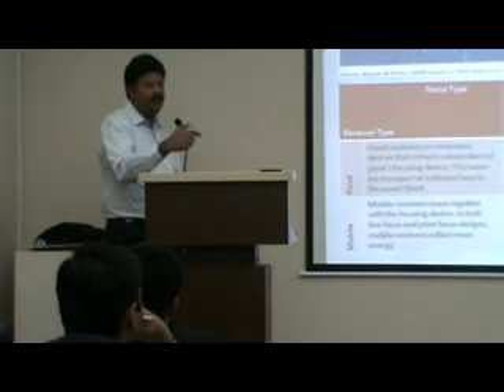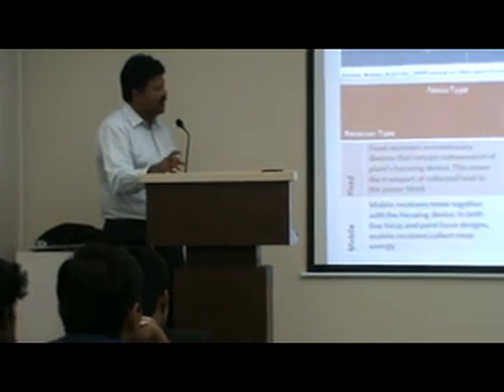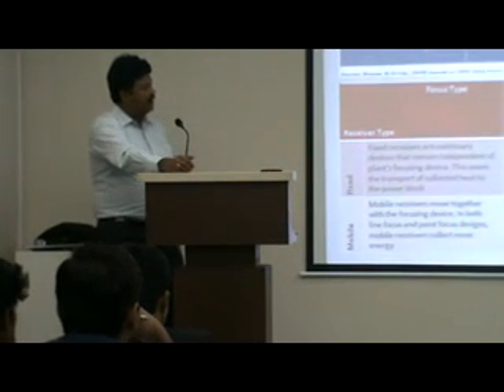Your supercritical thermal plants produce steam at 600 degrees plus, so their turbines are much more efficient, whereas for this you require a low pressure, low temperature turbine, so efficiencies are lower. Tower is the technology which looks like the future of solar thermal, because tower can achieve temperatures of up to 550 degrees centigrade. Then you get much closer to conventional steam temperatures in a power plant. We have about 3 plants running on tower technology today in Spain, 10-20 megawatts capacity each. But going forward, this will probably be the technology which takes over from parabolic trough.